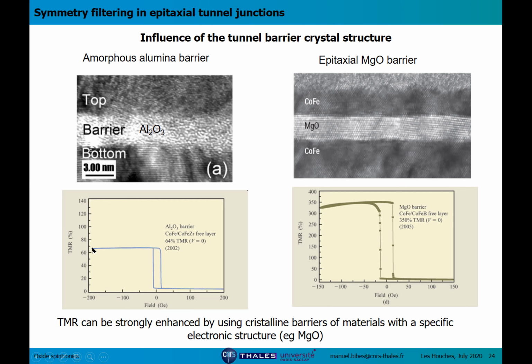I must mention here that the shape of the TMR curve is not the one I was showing you before, the nice symmetric one with two plateaus. This is because here again, on one of the electrodes, there is an antiferromagnet that pins its magnetization due to exchange bias. Okay, so basically here you see the switching of only one of the two electrodes and the other is fixed due to the exchange bias from the antiferromagnet.